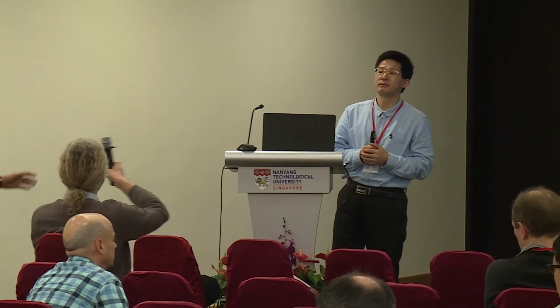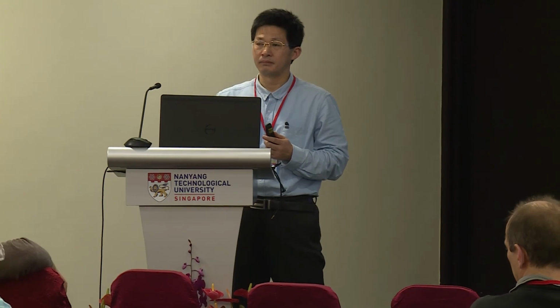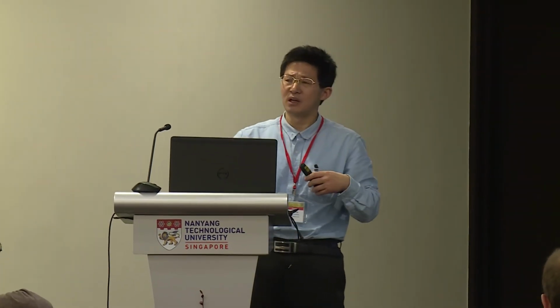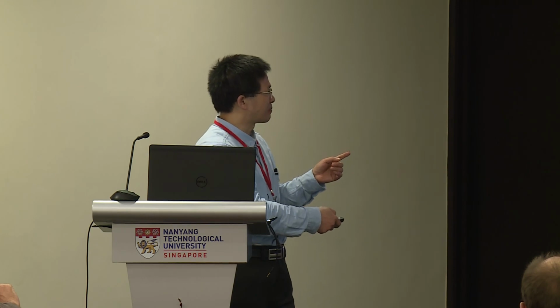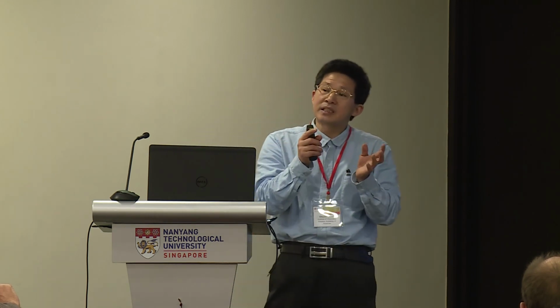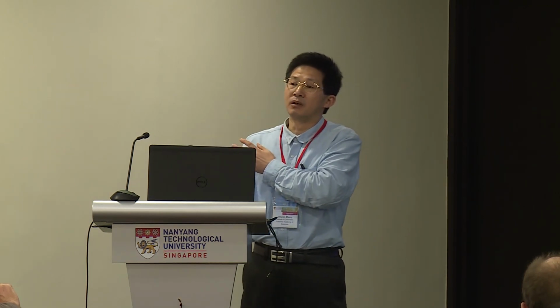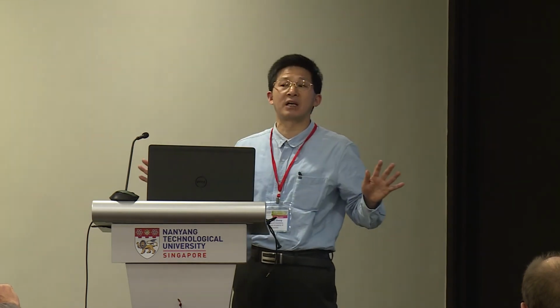Two quick questions. Related to catalytic activity, what experiments have you done to rule out the generation of heterogeneous manganese oxide that generates dioxygen? It's hard to rule out, but this sample actually comes from the calcium sample. We see high activity at the beginning, not after. That's because it becomes unstable and can be destroyed, so there's no activity at all.